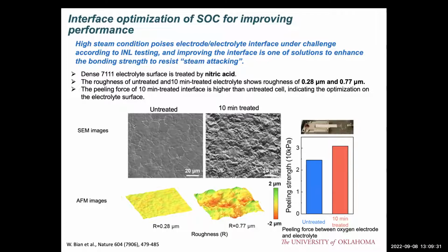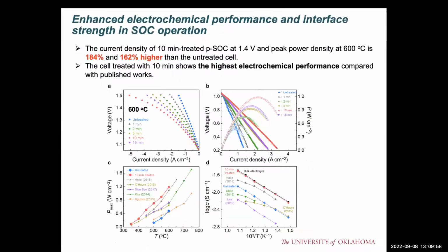After applying the electrode, we examine how easily we can peel the electrode off the electrolyte surface. So we examine the peeling force between the electrode and the electrolyte. After the acid treatment, we can see an increase in the peeling strength. Because of the increase in peeling strength, or we can say the stronger bonding strength between the electrode and the electrolyte, we can see higher performance and also better stability.